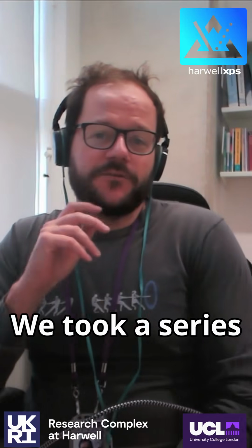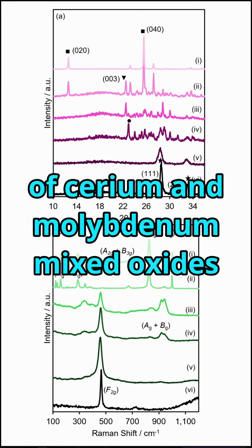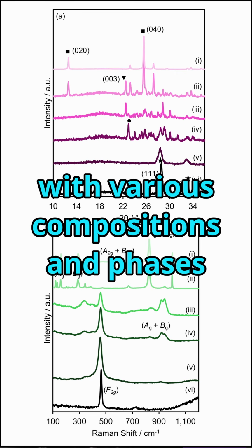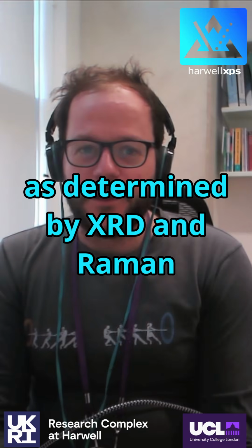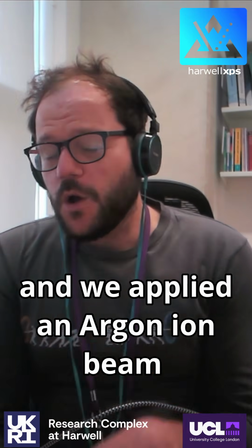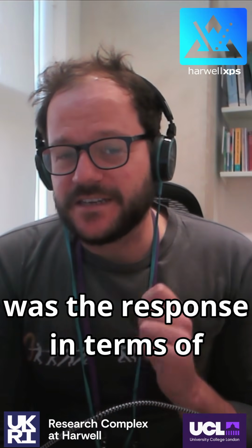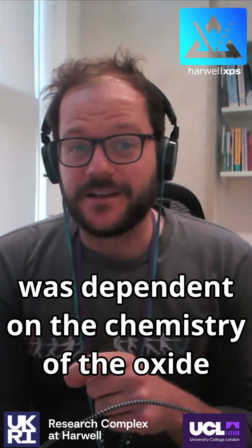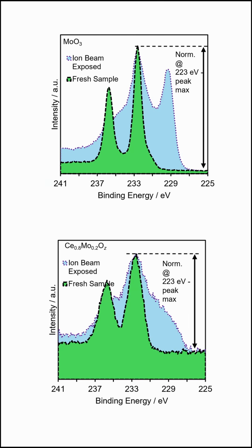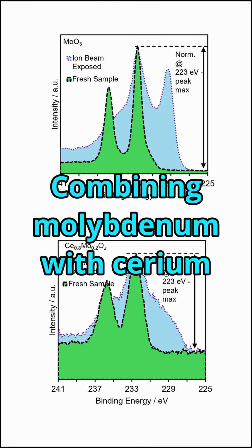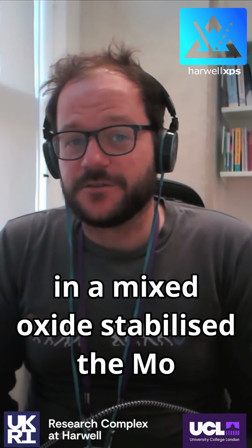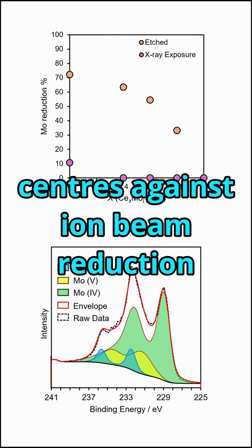We took a series of cerium and molybdenum mixed oxides with various compositions and phases, as determined by XRD and Raman, and we applied an argon ion beam. What we saw was that the response, in terms of the reduction chemistry, was dependent on the chemistry of the oxide in play. Combining molybdenum with cerium in a mixed oxide stabilized those molybdenum centers against ion beam reduction.